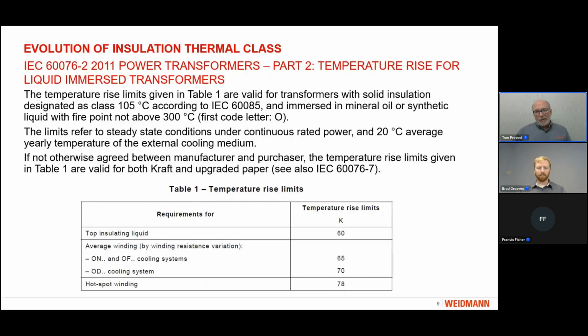And that's also discussed in 60076-7, which is known as the loading guide for over temperature. So in this case, the hotspot winding temperature, and these are rise limits, is 78 degrees because in the IEC world, they assume a 20 degrees average ambient temperature. So in IEC, the limitation for the hotspot is 98 degrees. And again, 98 degrees for IEC, and in IEEE, the limit using thermally upgraded kraft paper is 110 degrees, but the thermally upgraded paper or pressboard can be a lower temperature class.